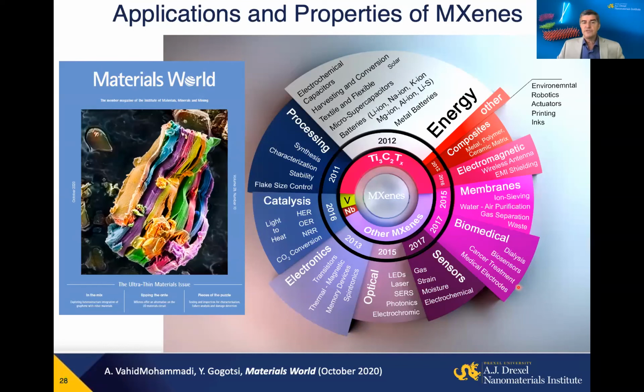Medical applications, photothermal therapy, drug delivery, medical electrodes, replacing silver, gold, platinum electrodes in electromyography, and other applications for cardiogram, encephalogram, and so on. And here, membranes for separation, where again you can use graphene oxide to make a hydrophilic membrane, but you can control transport by applying potential because of the conductivity of the material here. I talked about shielding antennas, and of course, you can also put MXenes into composite materials, ceramic, polymer, metal matrices, but you can also combine them with non-2D materials, for example, nanotubes, whether those will be carbon or molybdenum disulfide or others, developing further hybrid materials here.